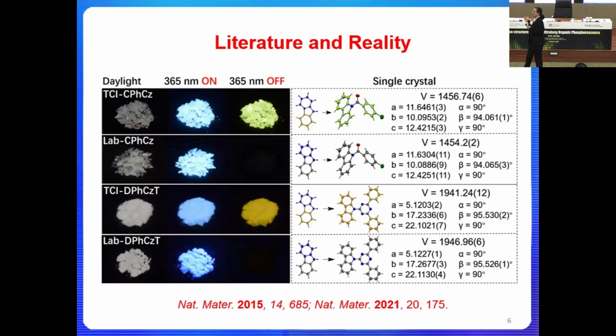But if we look at this compound, it's very stable, right? So that triggered us to understand exactly what went wrong, so that this phenomenon can disappear through the purification process. So we decided to synthesize the raw materials in the laboratory instead of getting them from the market. All right, so what we found out is if we use lab-synthesized carbazole to start with, we're not able to actually observe the reported phosphorescence.